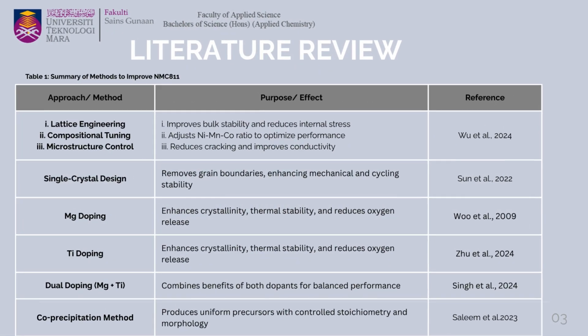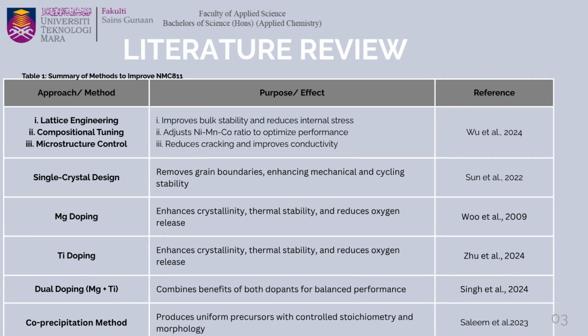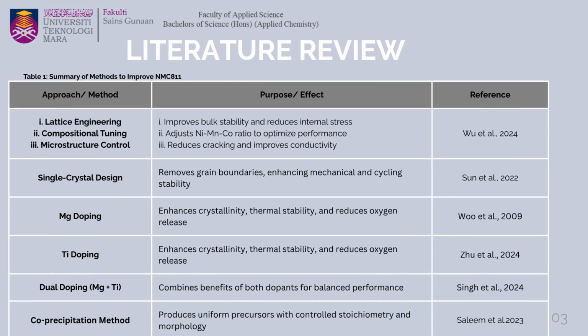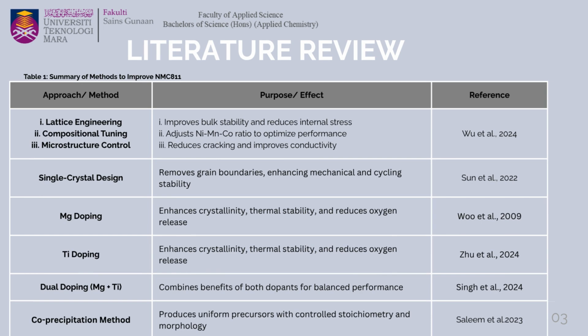Okay, next for the literature review. So, previous studies have proposed various strategies to improve the NMC811. Based on the paper by Wu, he reported 3 approaches. The first common approach is lattice engineering, where the crystal structure is modified to reduce internal stress and stabilize the bulk. Alongside this, compositional tuning, where the ratios of nickel, manganese, cobalt are adjusted to minimize the phase transition and enhance the electrochemical performance. And the third one is the microstructure control, which can reduce cracking and particle disintegration during cycling.